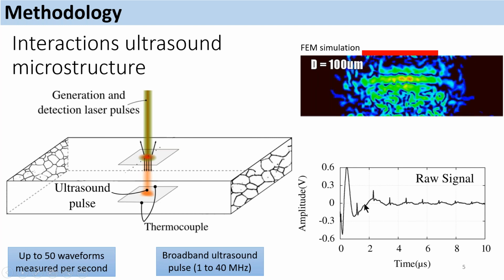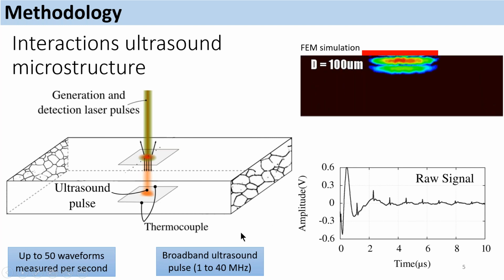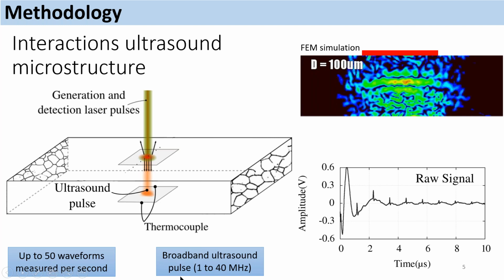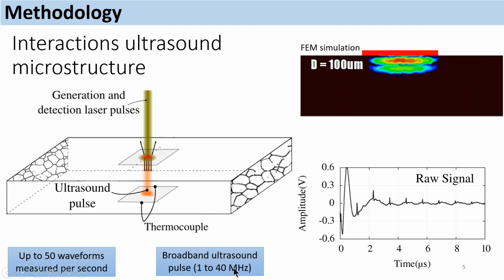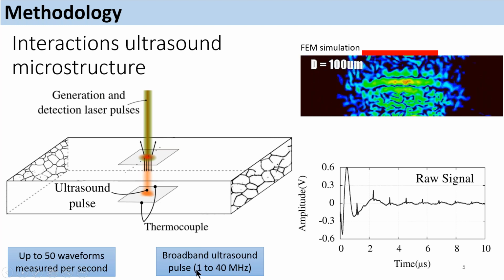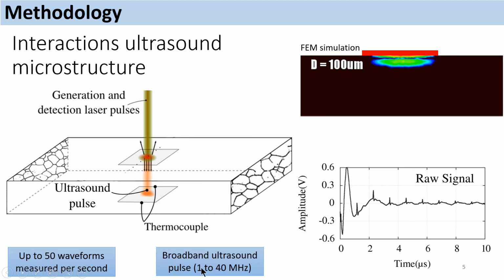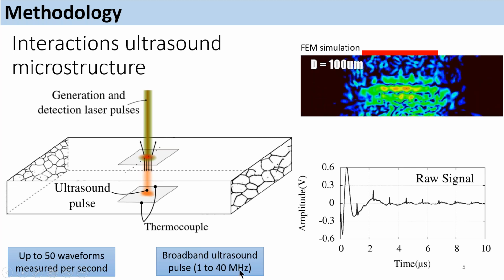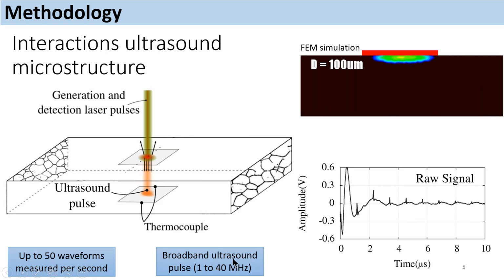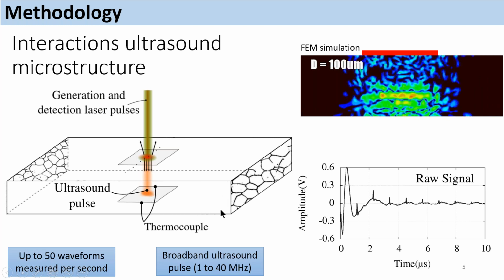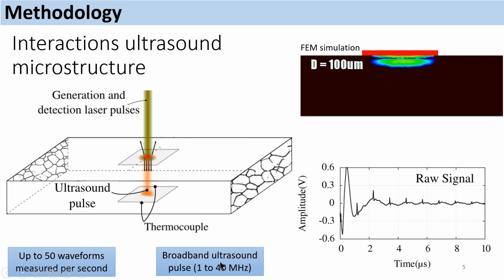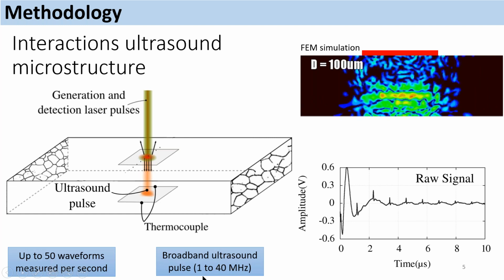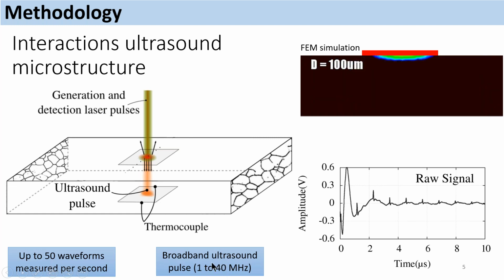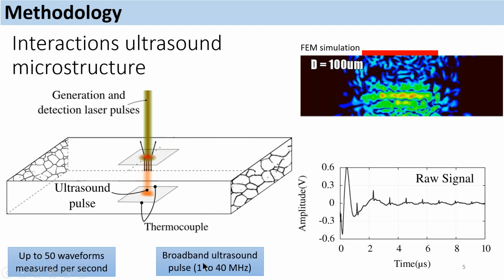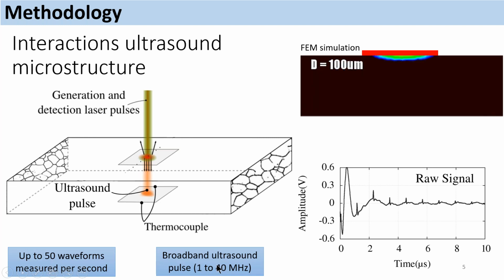Another important feature of this sensor is that it generates an ultrasound pulse which contains a broad range of frequencies. Typically, we can access frequencies ranging from 1 to about 40 megahertz. Of course, as we will see, depending on the microstructure properties, those high frequencies tend to be attenuated quite a lot. So the effective bandwidth that we can use can tend to be a little smaller.